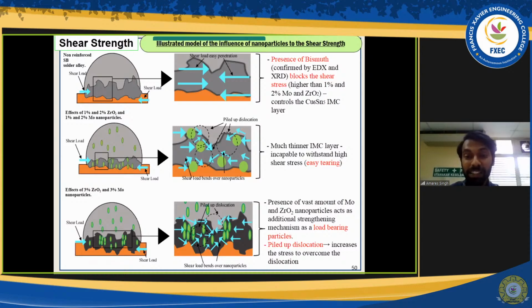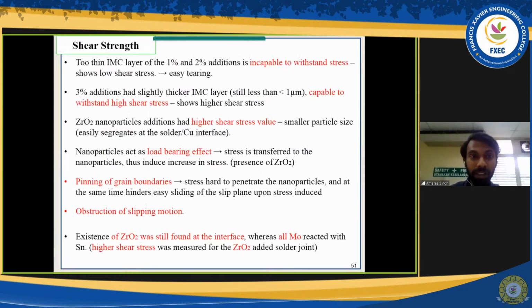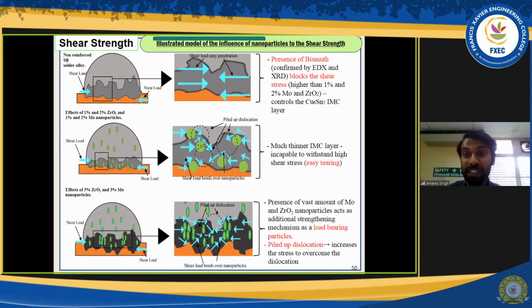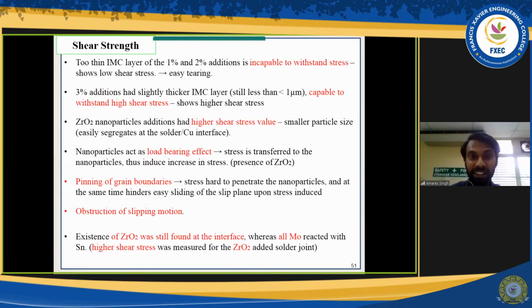So when the shearing is done, they act as another blocking or restriction particles. So that is why, of course, after I got the scanning electron microscope and XRD results, I came up with this model. So it could say that the zirconia 3% and the molybdenum 3% had the highest strength. So this is the explanation. Basically whatever I've shown here is written in this slide. So maybe perhaps I'll just summarize.